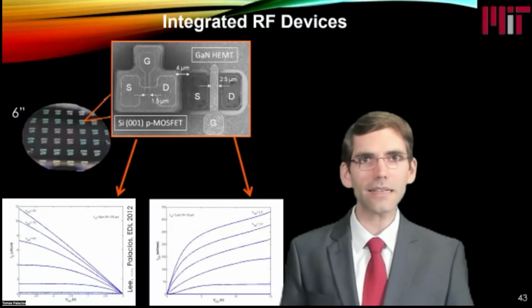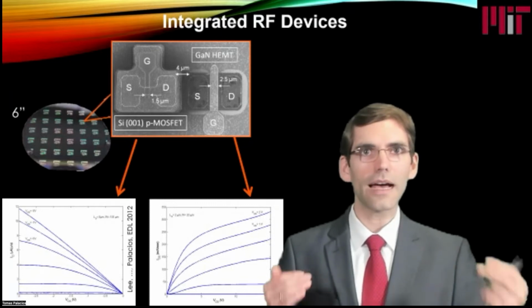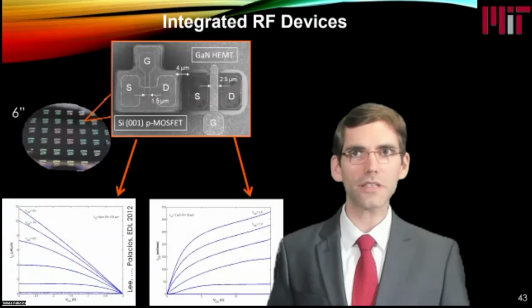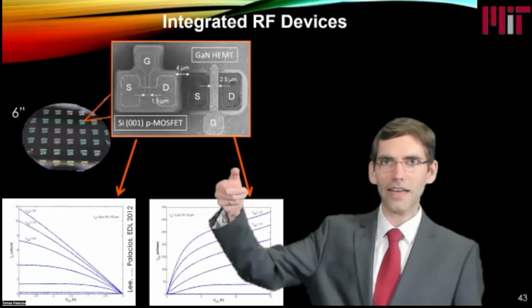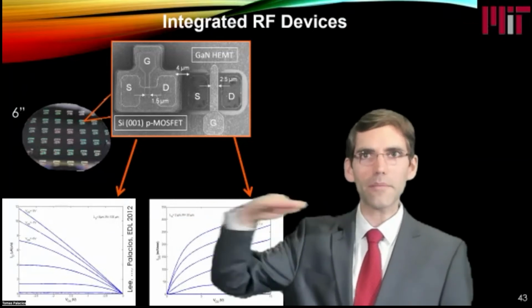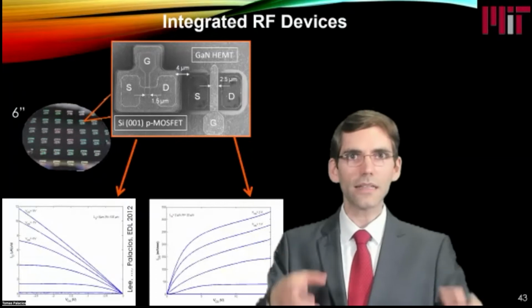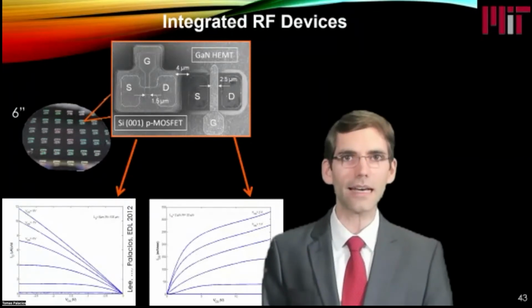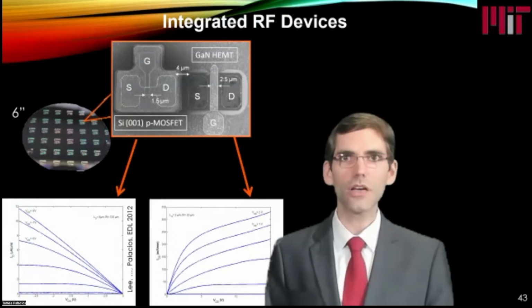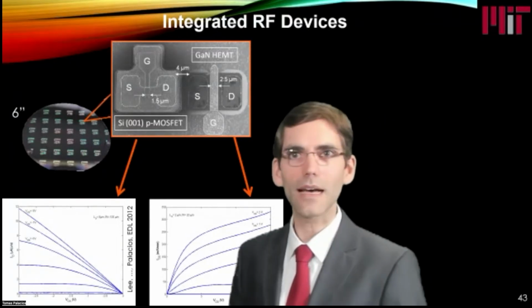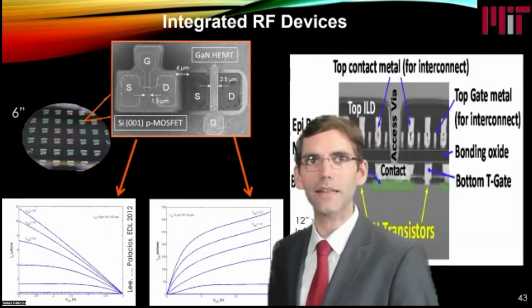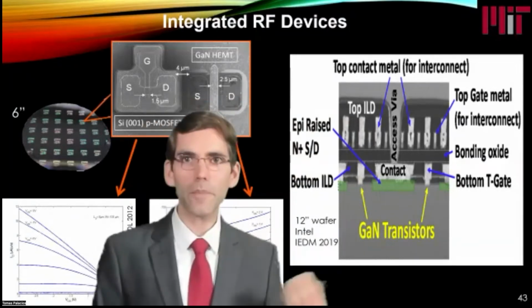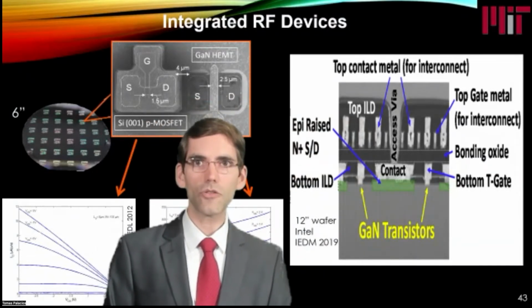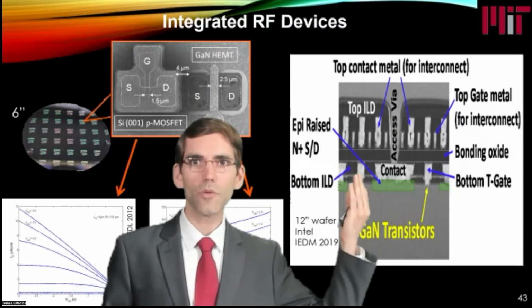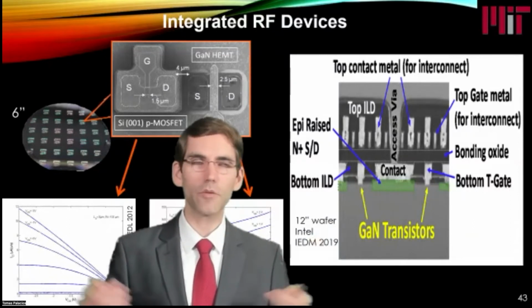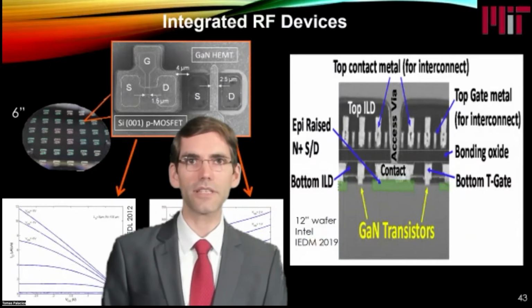The big advantage of gallium nitride is that it's very thermally stable and it can survive the standard thermal process of silicon technology. So we could take our special SOI wafer, fabricate silicon devices with standard technology, then open windows to expose the gallium nitride underneath, and fabricate the gallium nitride transistors at room temperature. And that's exactly what we have here, the silicon device, the gallium nitride device. And recently, the company Intel has taken a similar approach to demonstrate the integration of gallium nitride devices with silicon on 12-inch wafers, which I think is a truly remarkable result.